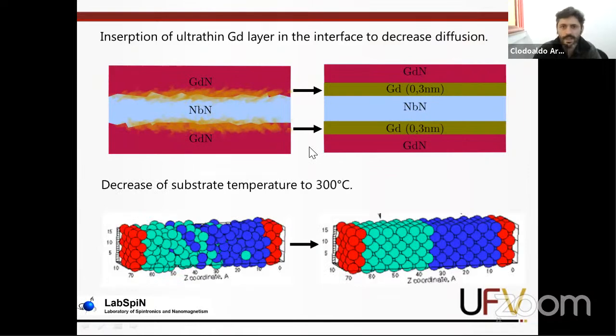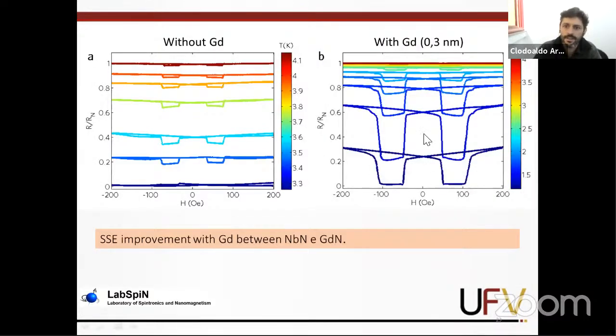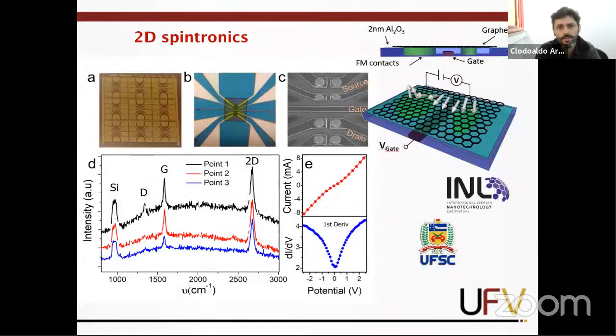And then, very near the critical temperature, we can have this very large magnetic resistance, close to infinite magnetic resistance. So these are superconducting spin valves. And then another thing we are interested in is 2D materials spintronics. We have tried here a spin FET, so it's like a CMOS transistor, but using ferromagnetic electrodes, tunnel ferromagnetic electrodes, to inject and collect spin currents.